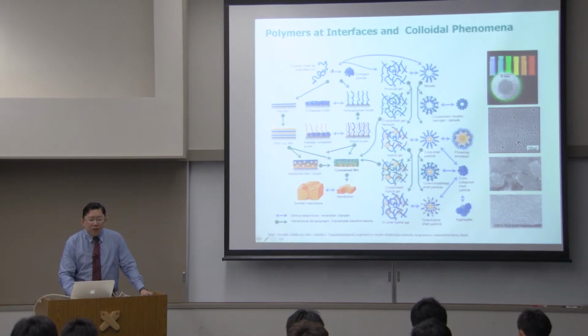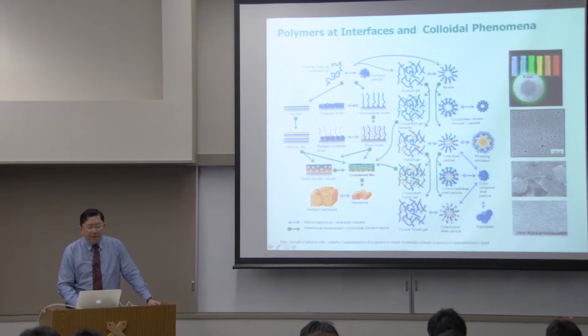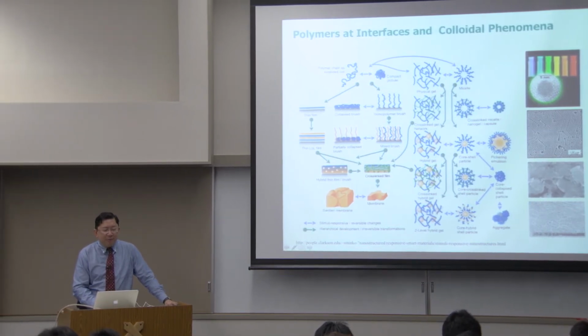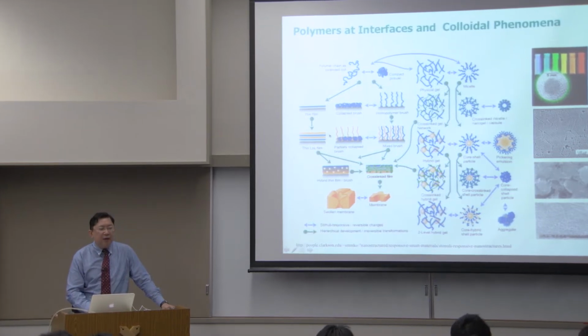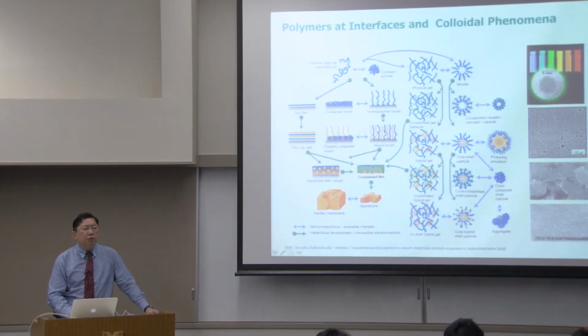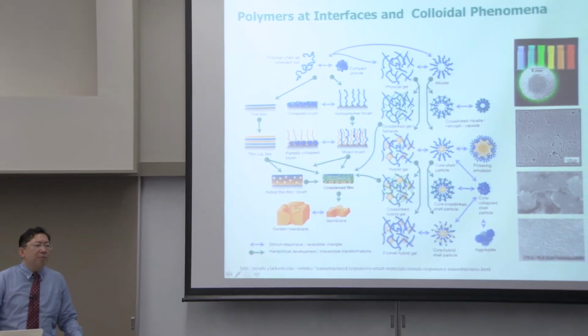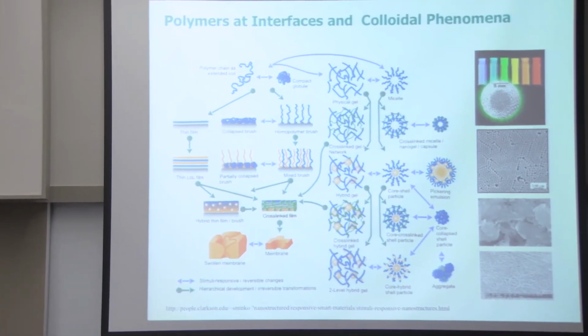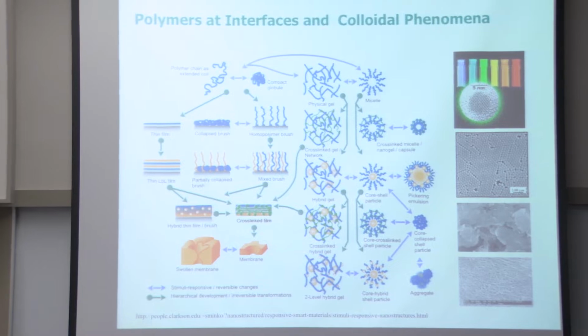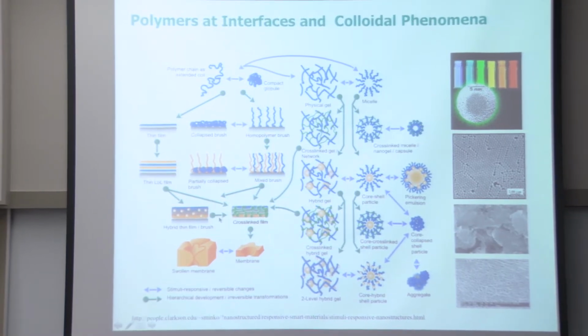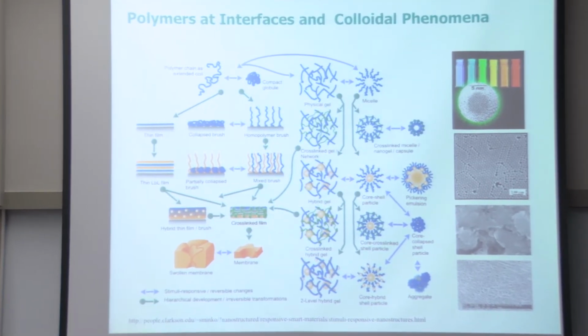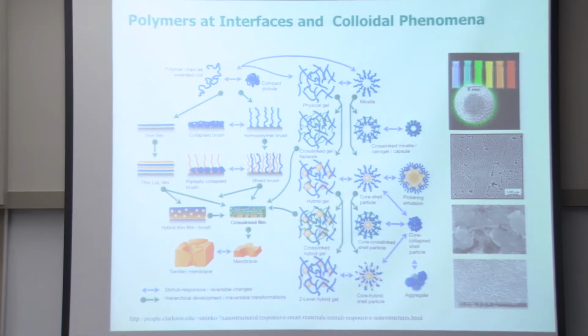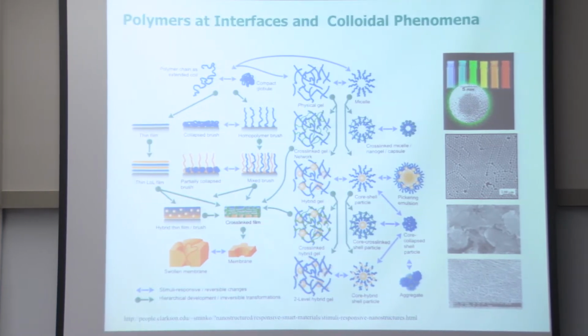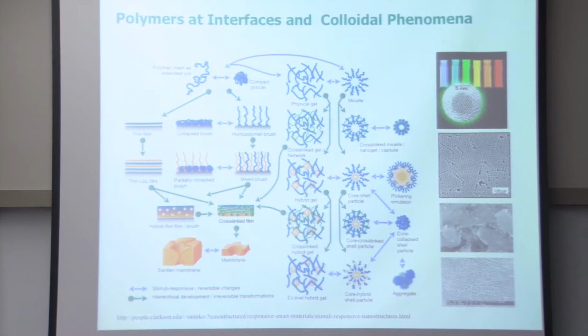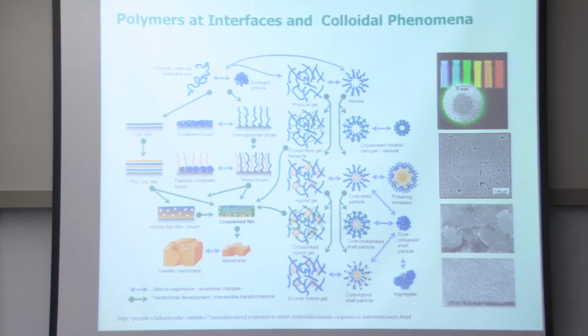In one occasion, you can have a polymer forming films or forming polymer brushes, a thicker film involving layering or structuring to form blends or polymer brushes with different grafting densities. And then this can result into membranes or thicker films. In other words, from the nanometer level and up, you can make polymers stand up or lie flat or produce different types of collapse regimes.